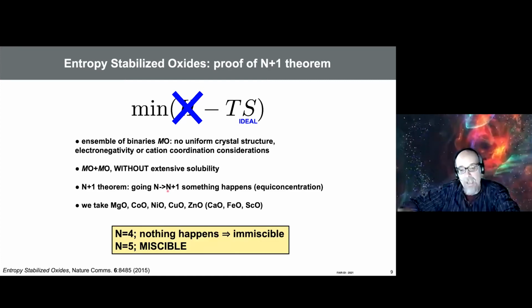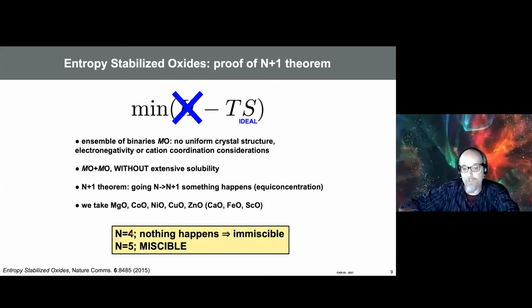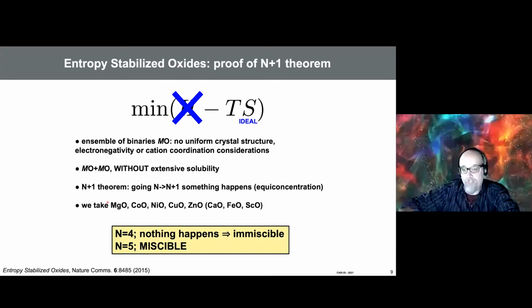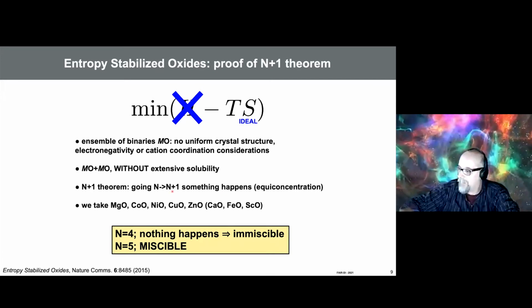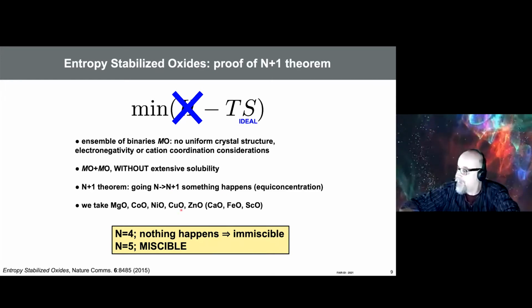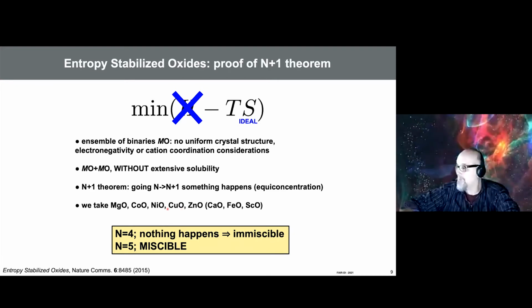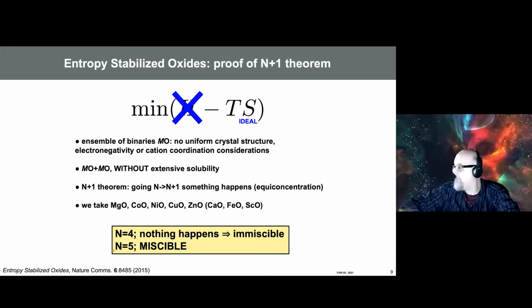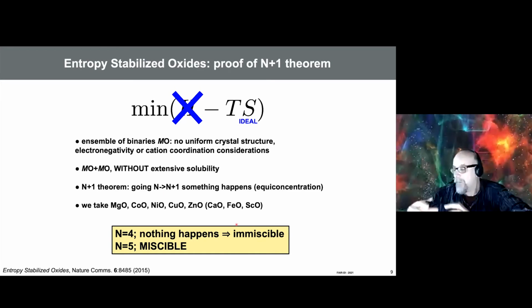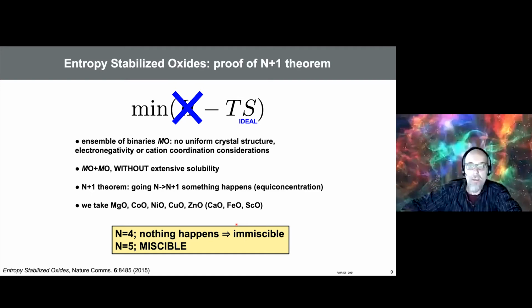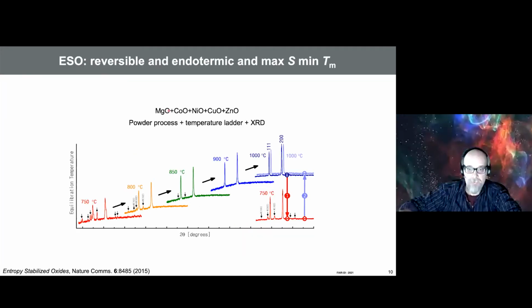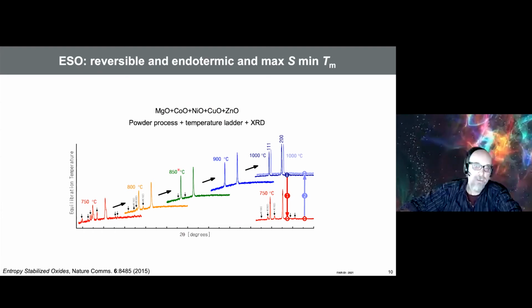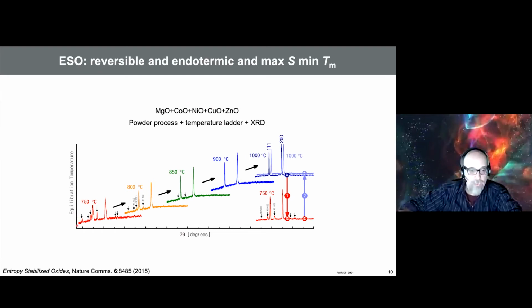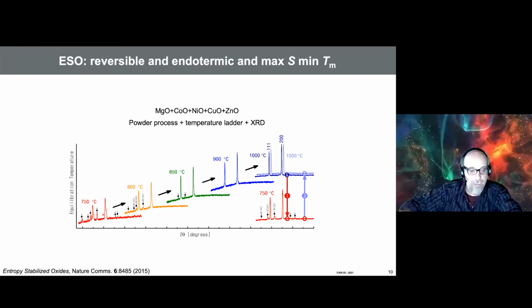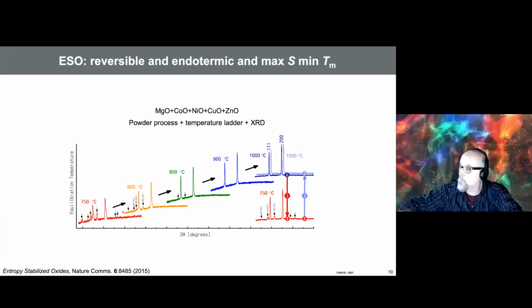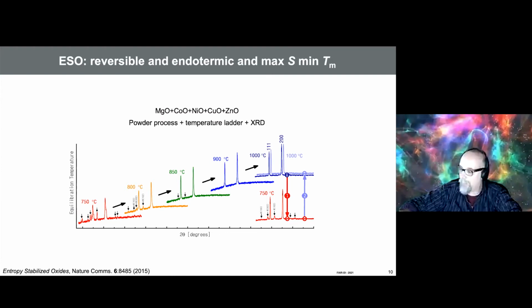Yes, it does. And we found that the threshold was to go from 4 to 5. So every 4 of these 8 metal oxides do remain phase separated at around 1000 Celsius, okay? But if you take 5 of them, any 5 of them, you have the miscible. This creates a solid solution. Examples, all right, this is the first example we did. We took equicomposition to maximize entropy. So you see that at low temperature, each one you have the fingerprints. This is 2 theta, right? You have the fingerprints of the powder of the precursors.